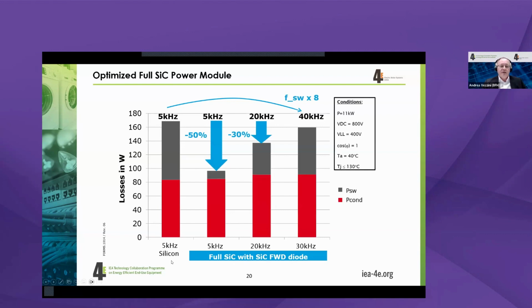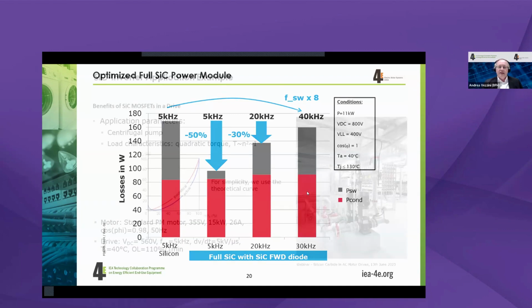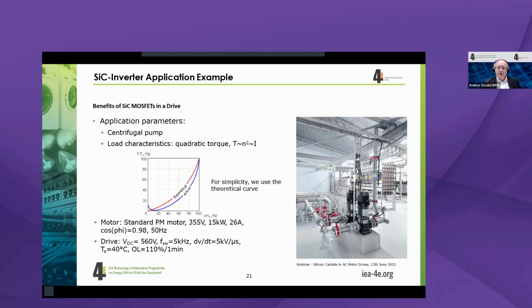So compared to a 5 kilohertz switched silicon inverter, where you have roughly the same amount of switching losses and conduction losses, if you run the same inverter now with a silicon carbide module with a freewheeling diode also on silicon carbide, we have a reduction of almost 50%, because the switching losses really go down compared to silicon. And therefore, we can go higher again with the frequency, and we'll still reach slightly smaller or similar losses.